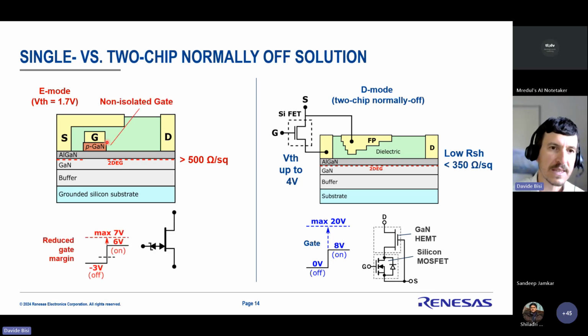The key thing here is that now the gate is not isolated. You see there's no dielectric between the gate and the semiconductor. So that means we now have a reduced gate margin. Because the threshold is low, we need a negative gate drive to turn it fully off and for switching during applications. We turn it on at 6 volts, but at 7 it's already the maximum. So that's posing some limitations on how we drive it and how careful we have to be with this device.